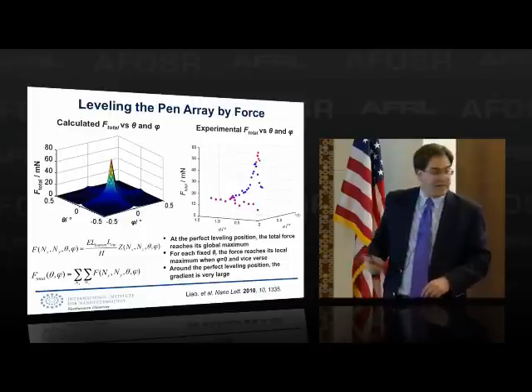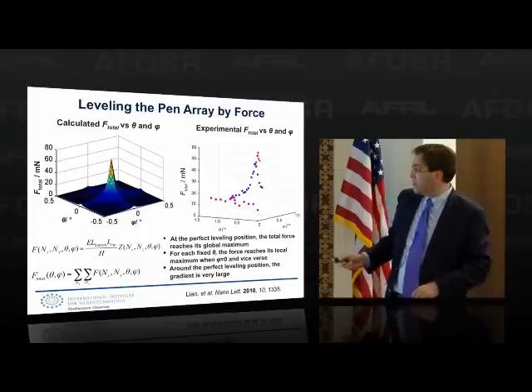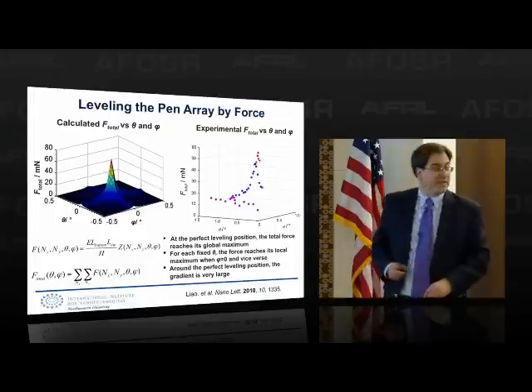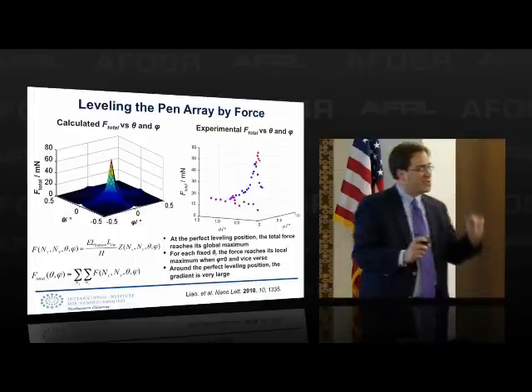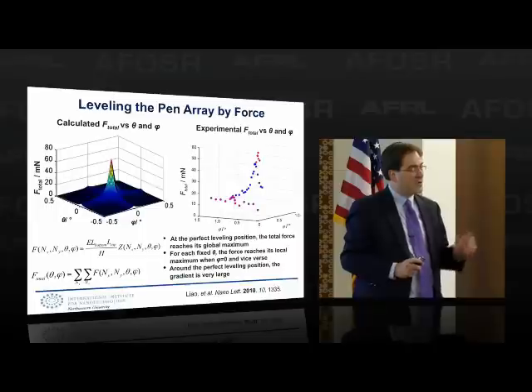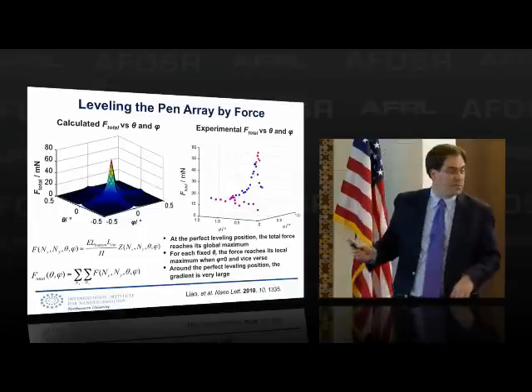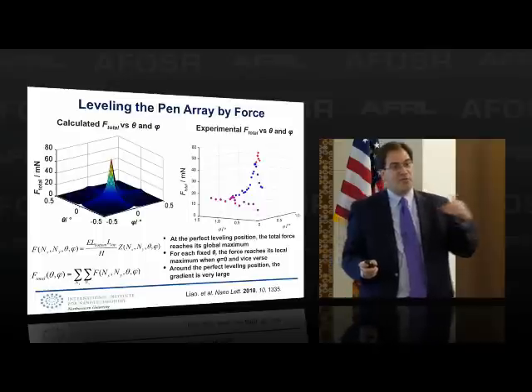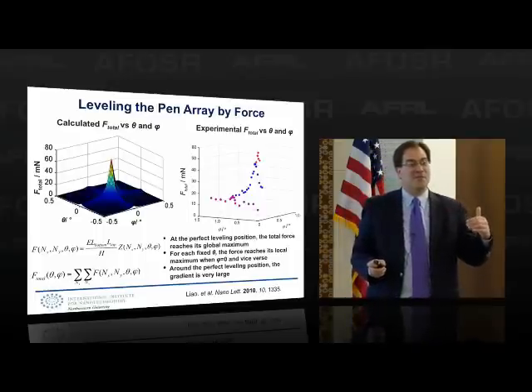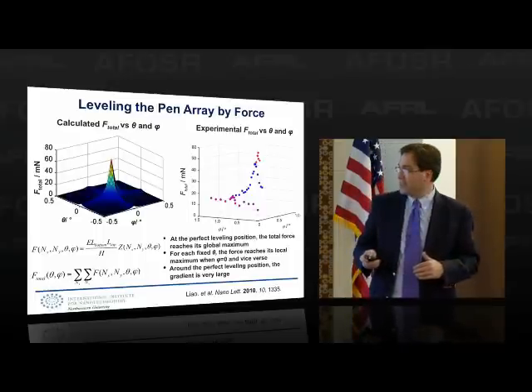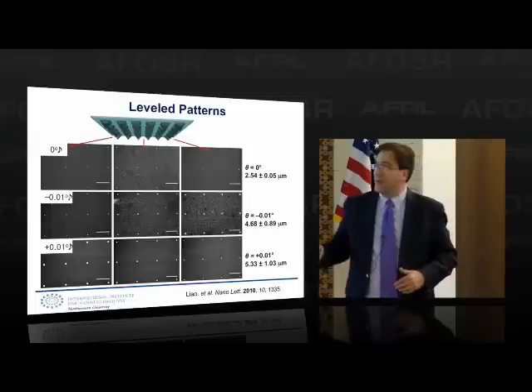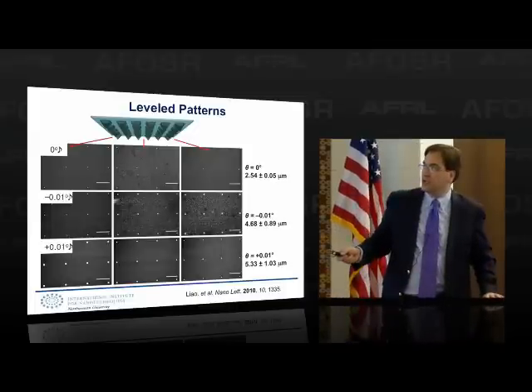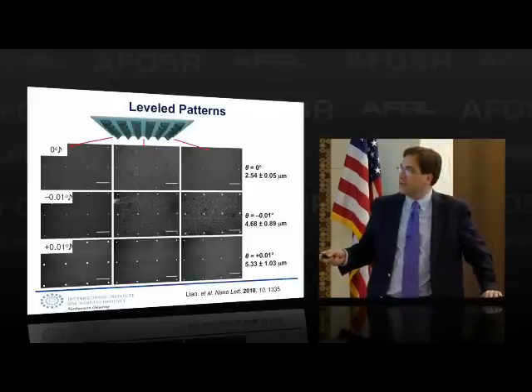So we keep that fixed at that point. And then we tweak phi, and we see another local maximum. And then we adjust right around the sweet spot, and you can see the global maximum here. And when you do that, in principle, the array now is perfectly level. Now, you can test that. You can do that by coating this with molecules and then printing on a gold substrate. And here you can see the perfectly level array.